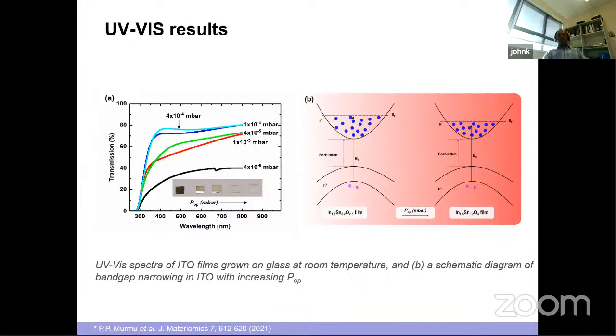Again, you're narrowing the band gap by increasing the operating pressure, which increases oxygen vacancies, which we call the reverse Moss-Burstein effect. So that's another effect happening in the ITO. Many people investigate ITO for flat panel displays, thin films, and all those applications, but only very few reports looked at the thermoelectric side.